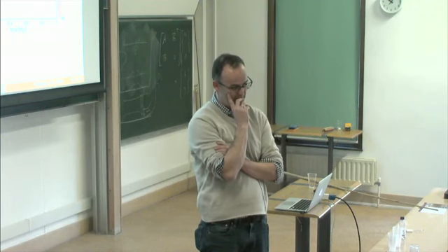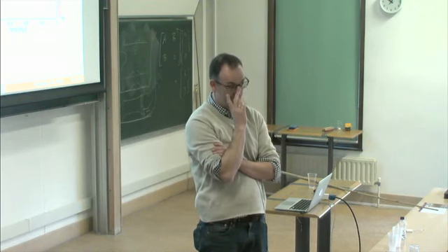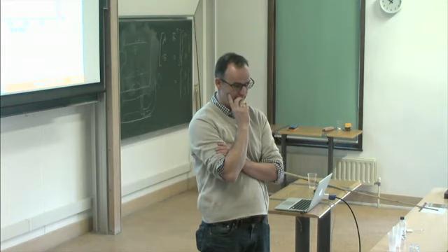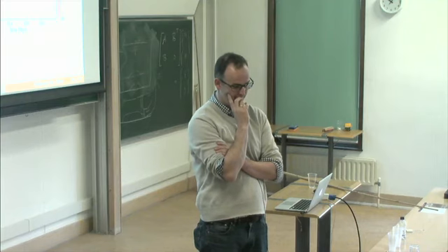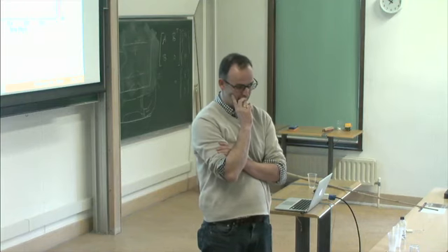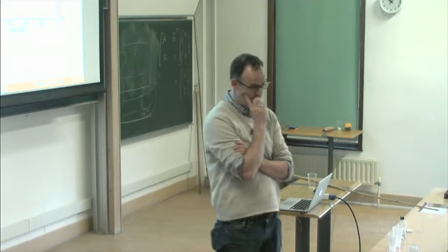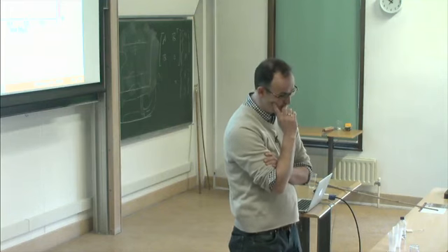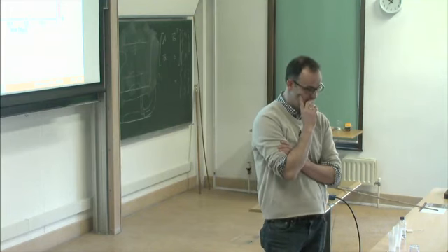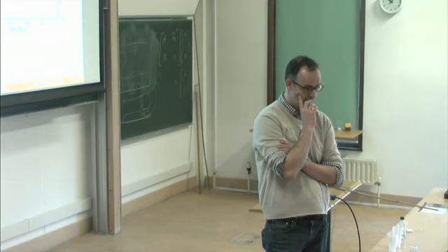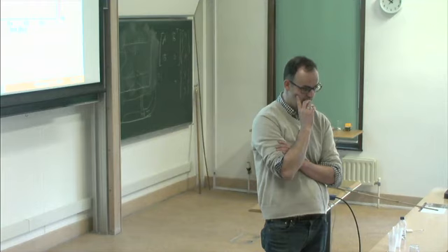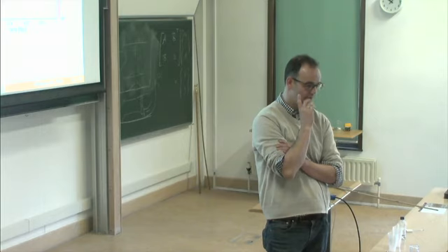The low energy surfaces could be the same ones as the short edges, or they could not be. It depends on which slip system you have. If you have both crystal preferred orientation and shape preferred orientation, what fabrics we have. Usually, the fabric pictures that I've seen seem to suggest that you have both. And the face that is proposed to be preferentially wetted is the one that orients along the flattened planes also, which is sort of what we see.